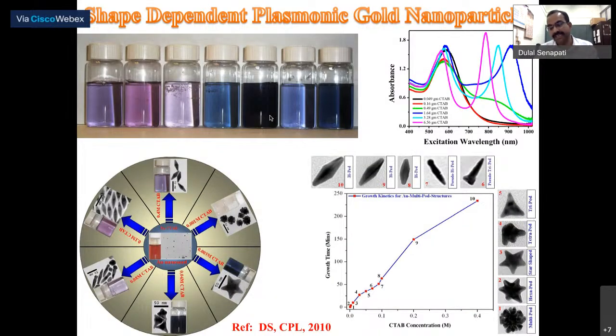Not only that, the shape also is a factor. How does the shape actually change? There are several factors. Simply think about changing the viscosity. Long back, we did some experiments where we changed the viscosity by increasing the concentration of the surfactant. Once you increase the viscosity, the movement of the gold atoms will be slowed down. Once it slows down, their crystallization will be much more patterned and they will give more directed nanostructures. You see, at the beginning this one looks like a flower shape. That's because here the concentration of the surfactant is least. So these gold atoms are very free. They come from all directions and make a totally isotropic particle.